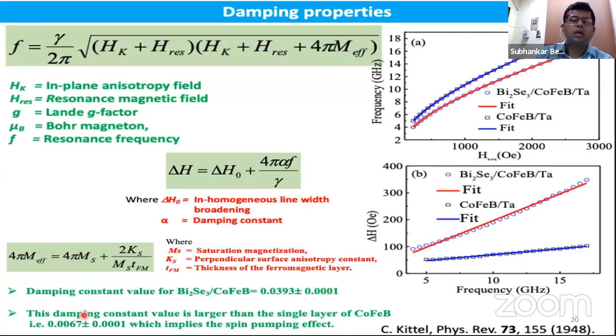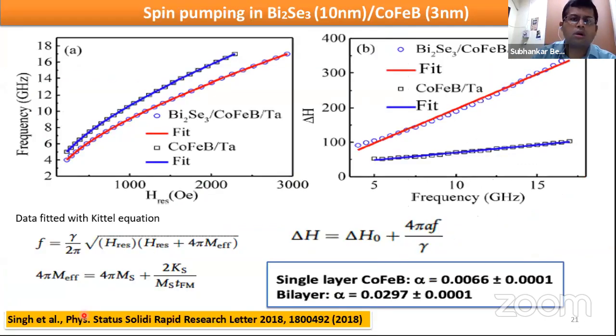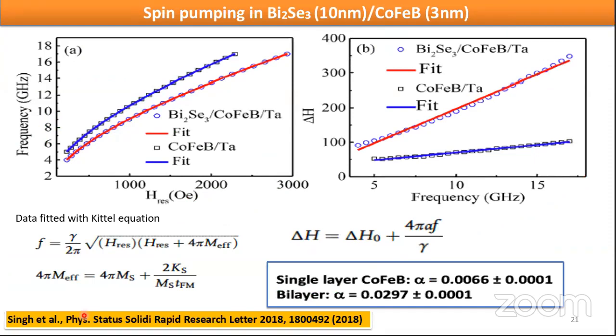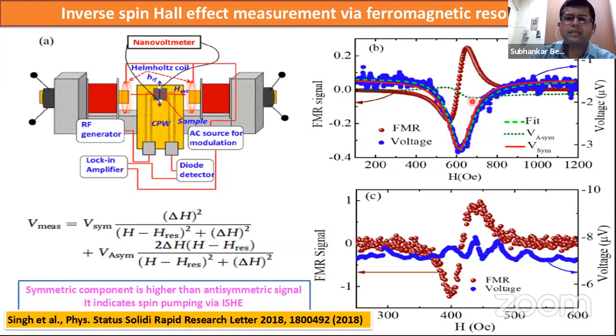In order to conclude or understand more about the spin pumping, we did this ISHE measurement, so inverse spin Hall effect, and then we found beautiful signals. So this red curve is basically the FMR spectra, and these blue data points are basically our ISHE. And you can also rotate the sample, and this blue curve should change its sign. So that clearly indicates that it's a spin pumping.